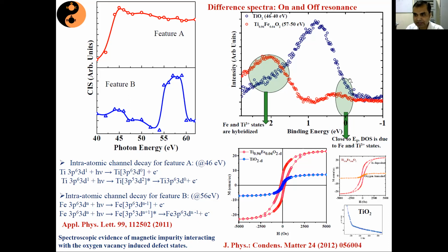So if you look at after annealing, the titanium 3 plus is decreased as well as there are no free carriers available. Since there are no free carriers, there is no carrier mediated magnetization and the magnetization has considerably dropped down. And that is also reflected from the semiconducting behavior of this TiO2.